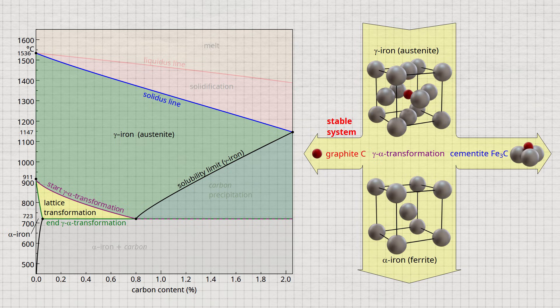As the name suggests, this compound is very hard and is largely responsible for the increase in hardness of the steel. Cementite precipitation can be achieved not only by faster cooling, but also by additives such as manganese. The precipitation of carbon in the form of cementite is also referred to as a metastable system in the thermodynamic sense, since the iron carbide compound would decompose into the thermodynamically stable graphite form by diffusion processes at sufficiently high temperatures and long annealing times.